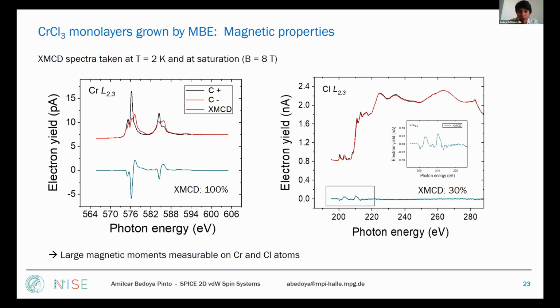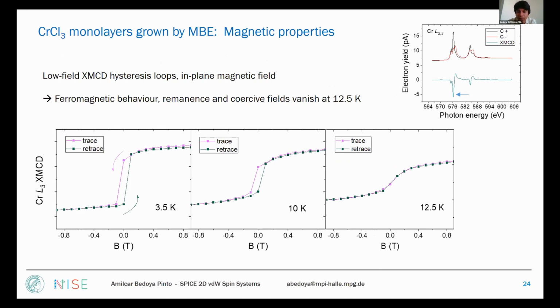Now the question is, if we have a remanence, because this is at high fields, what happens if we do a field-dependent measurement? And actually that's the key point of the talk, that we were able to see in the low field region a hysteresis loop, an XMCD hysteresis loop, and we see a phase transition between 10 Kelvin and 12.5 Kelvin. And here you see very beautifully how the hysteresis loop closes when you increase the temperature. And that hints that indeed we have long-range magnetic ordering in this sample.